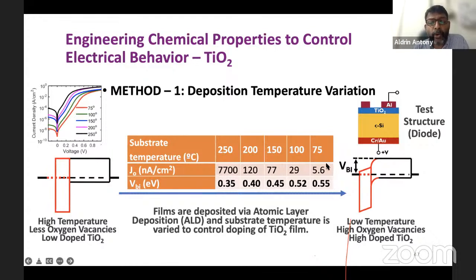And we found that, at the lower the temperature of the substrate, this is actually done using a thermal ALD. And by changing the different temperatures, we found it is better to have the built-in potential, that is the bending that happens when P and N junction forms. That bending was high, that the VBI value was high for a low temperature. So that was something around 0.55 volt that we are getting for the built-in potential with the titanium dioxide.